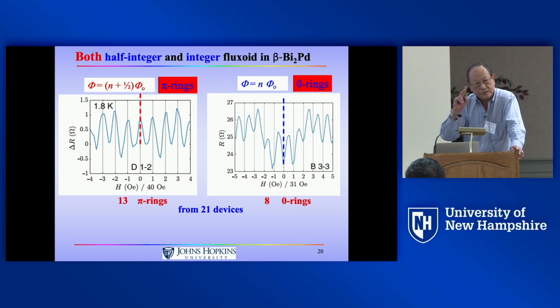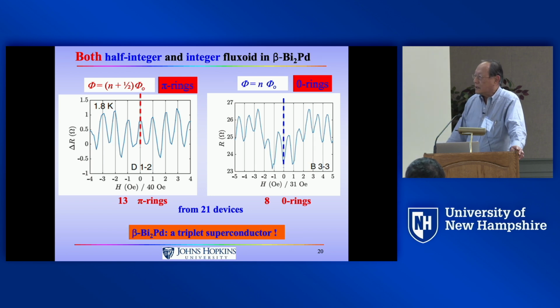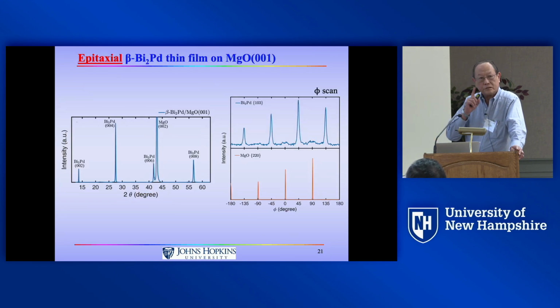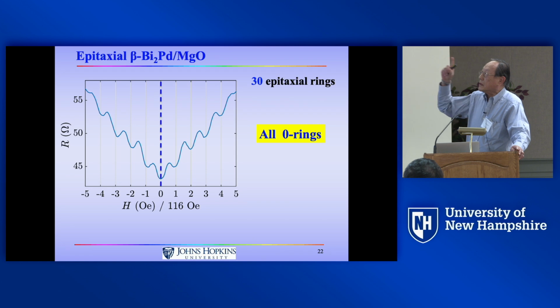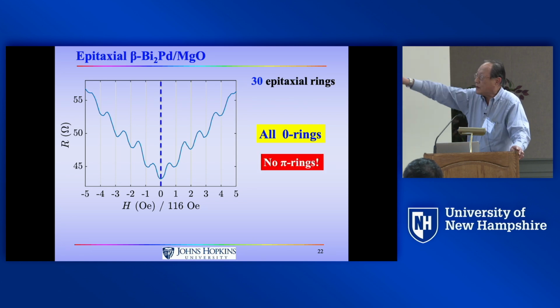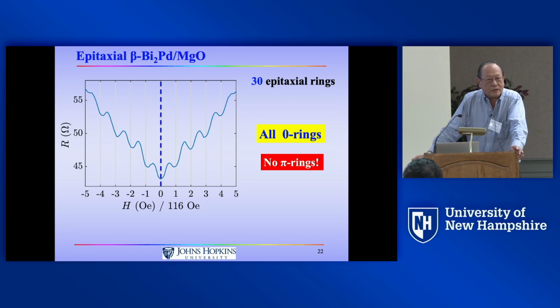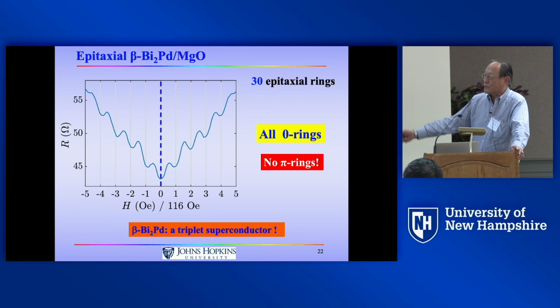So it survived the second test. There's a third test. You can also make epitaxial film. Those of you who make film know, you choose the right substrate, you can make epitaxial film. When you have epitaxial film, there's no grain boundary. You better not see half flux. So we make 30 epitaxial rings. We saw 0 pi. Everyone is an integer flux. Okay, so we can say for sure this is a triplet superconductor.